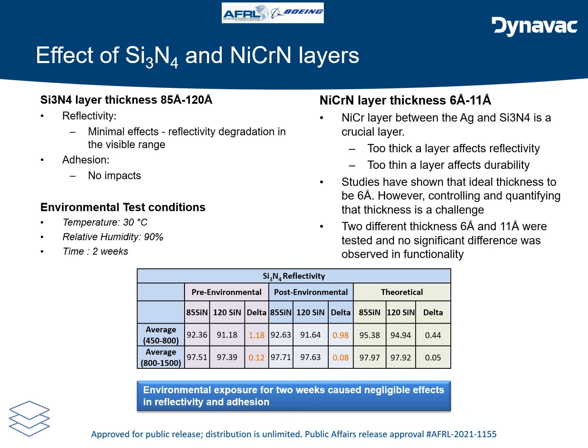We did the same on the interlayer as well, the nickel chrome nitride layer. This layer is so thin and it's very critical to maintain that thickness because too thick a layer affects reflectivity, too thin a layer affects the durability of the films. Studies have shown that the ideal thickness is 6 angstroms. However, controlling and quantifying that thickness is pretty challenging. Hence, we started off with 6 angstroms and we doubled it approximately to see if there was any noticeable change.